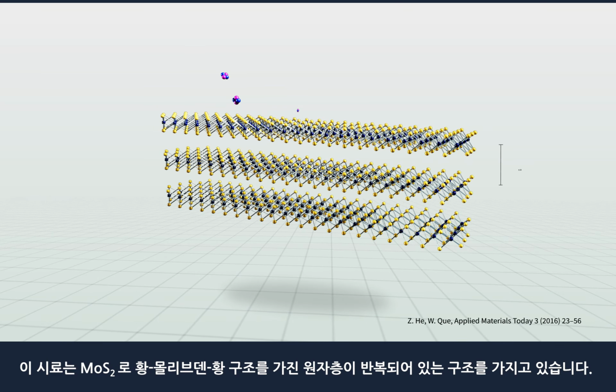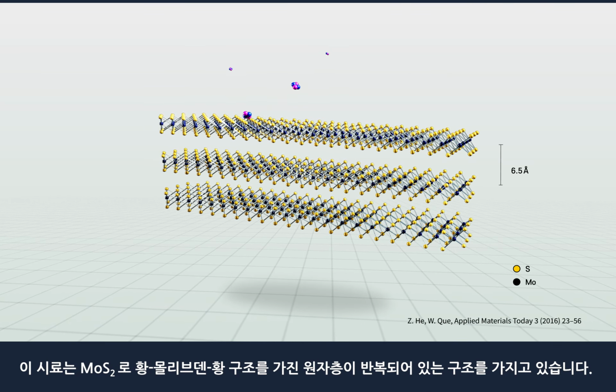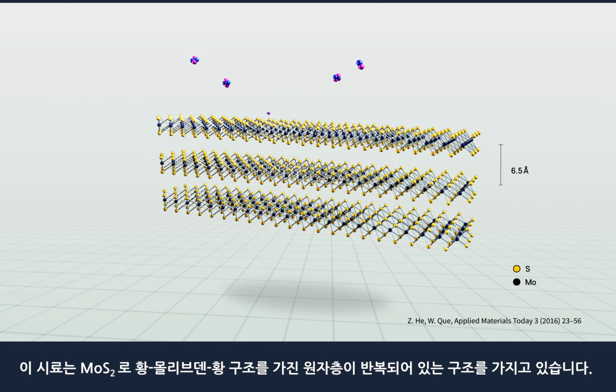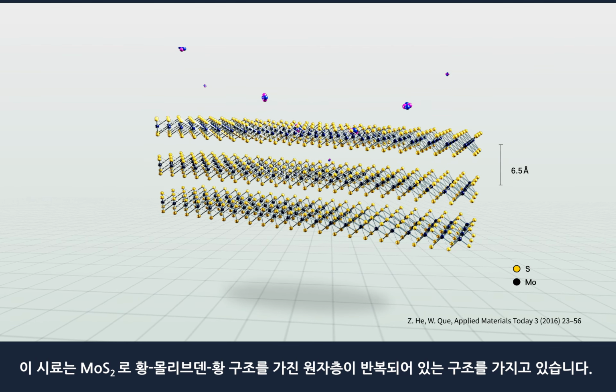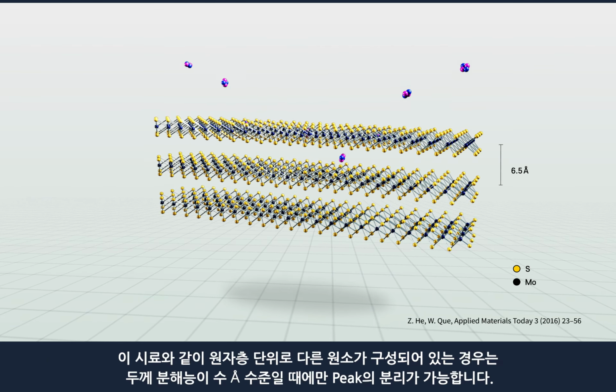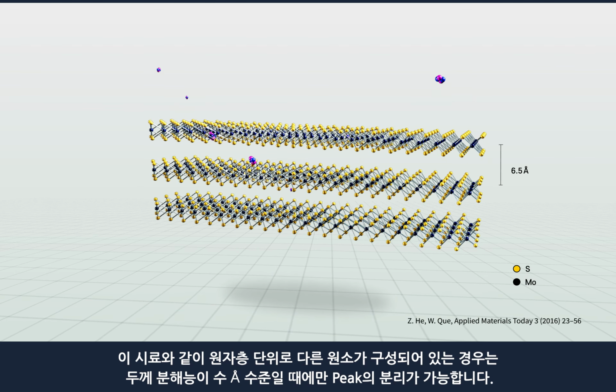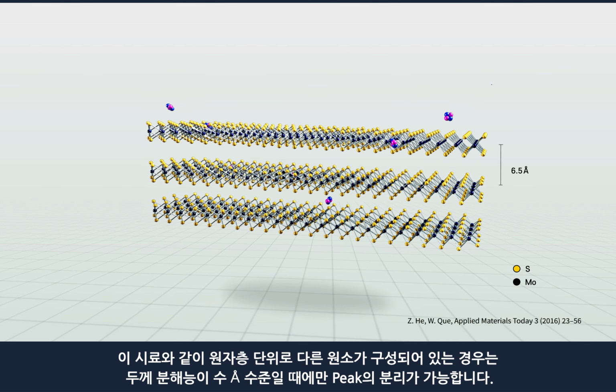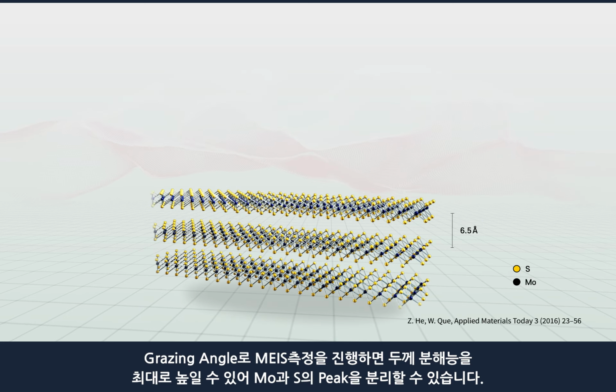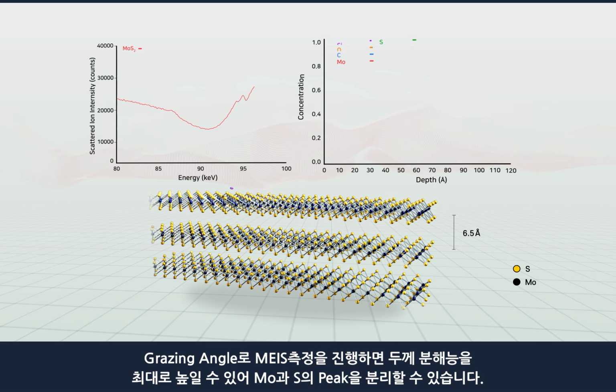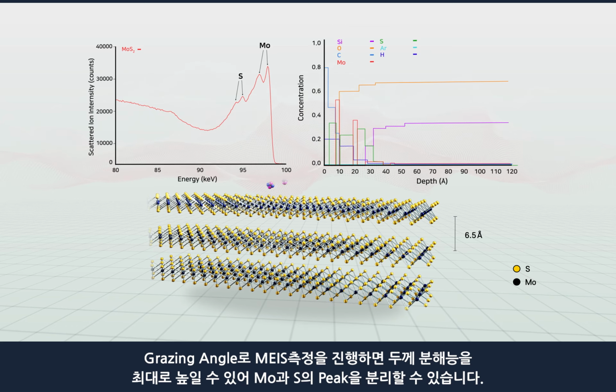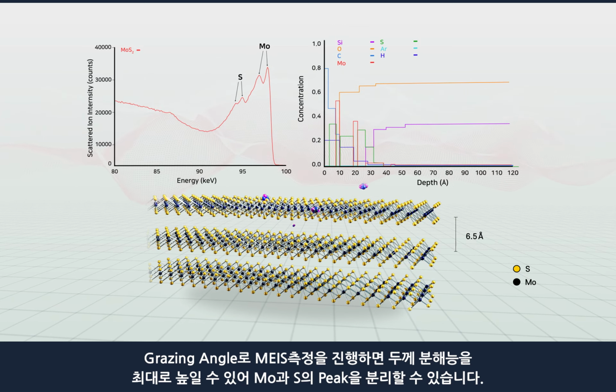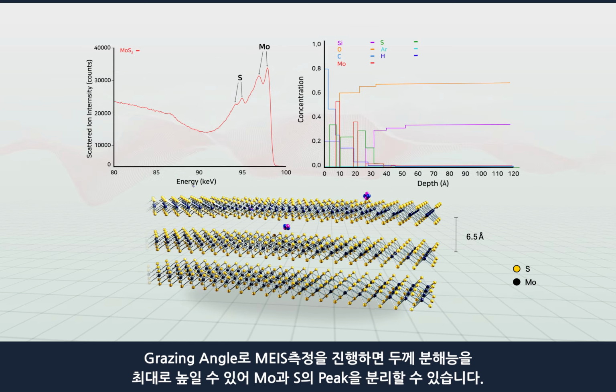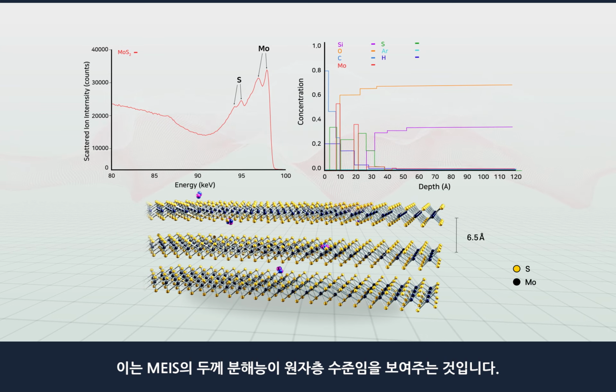This sample is molybdenum disulfide, with a structure in which atomic layers with a sulfur-molybdenum-sulfur structure are repeated. When each atomic layer consists of a different element, peak separation is only allowed when the thickness resolution is on the order of angstroms. Performing MEIS measurements at a grazing angle maximizes the thickness resolution and allows separation of the molybdenum and sulfur spectra. This indicates that the thickness resolution of MEIS is equivalent to the level of the atomic layer.